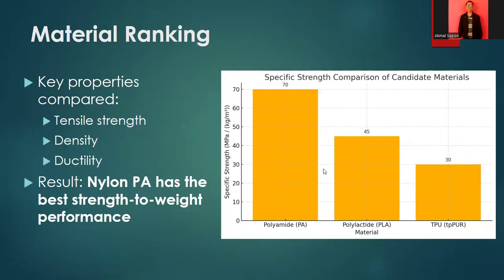Next is material ranking. Here we compare the specific strength of each candidate, that's tensile strength divided by density. Nylon PA stood out with the best specific strength, meaning it provides strong mechanical performance at a lower weight. TPU was more flexible but had low strength, while PLA is biodegradable but brittle and more suited for rigid packaging than structural components.